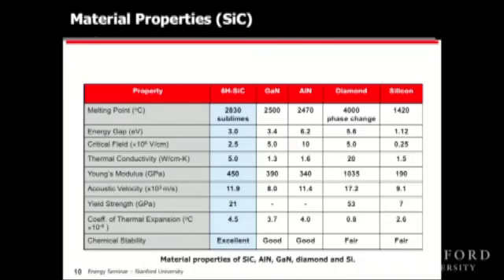So it takes a lot of energy to break apart the silicon and carbon bonds between the atoms in the silicon carbide. Also, it's a wide band gap material, around 3 eV, and so it takes a lot of energy to generate thermal carriers. Electrically, this material is very, very stable. In addition, its chemical stability is very, very superior to all of these materials. There are no wet chemicals that etch silicon carbide at room temperature. It has a very stable oxide layer, silicon dioxide.